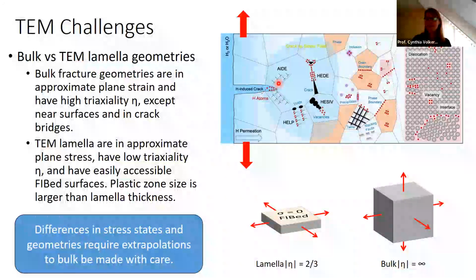Our observations are made on specimens that are in a completely different stress state than the bulk specimens. Plus, there are very easily accessible surfaces, which are not so accessible in the bulk specimens. And these are surfaces that have often seen various processing, such as focused ion beam machining. So there are really significant differences in the stress states.